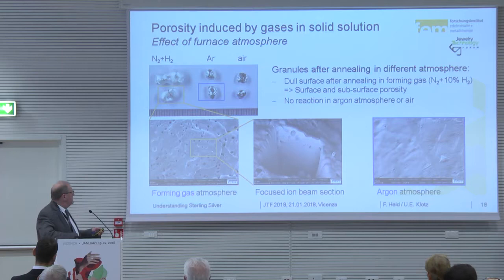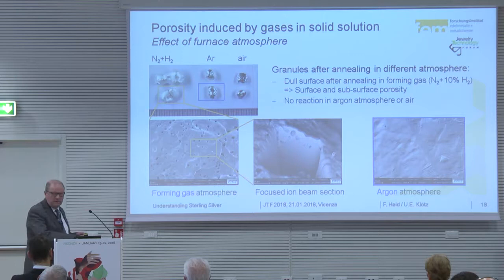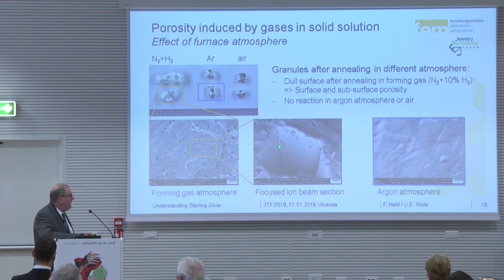And so we see the granule which we annealed under forming gas lost the shine, and we see on the surface a lot of pores. We made here a cut with focused ion beam, and we see that there are pores in the granule annealed in forming gas atmosphere. On the top surface there was no reaction.